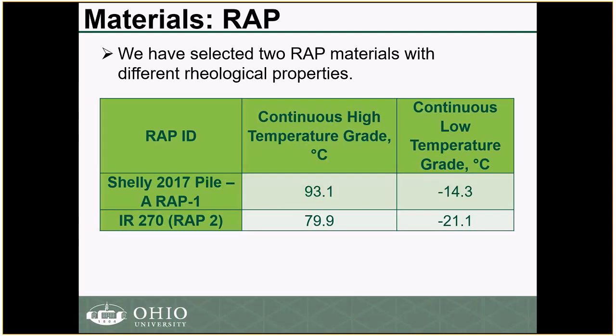We obtained RAP from different contractors, and based on that we selected 2 RAP materials. What we tried to do was select RAP materials whose binders have different rheological properties, and you can see a summary of those properties there, the continuous high temperature grade and the continuous low temperature grade, and you can see that there is a significant difference. Most of our work was with the first one, obtained from Shelley Company in 2017, Shelley 2017 Pile A. That's the designation for their RAP pile.